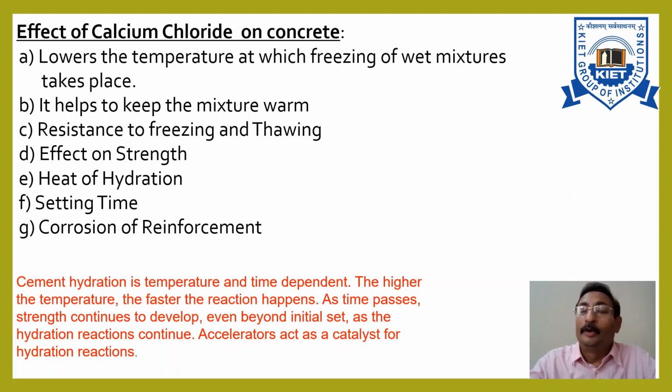Some of you may ask why we should not use calcium chloride in pre-stressed concrete. It is because there is possible stress corrosion in pre-stressed steel.